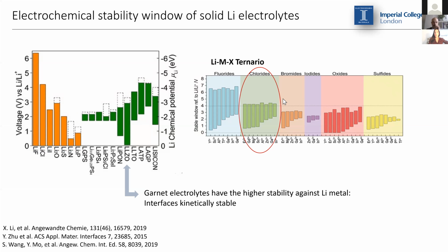If we look to the chlorides, this electrochemical stability window increases a lot, and they are actually very good at high voltages, but they don't have good stability at low voltages, and they are not stable against lithium metal. The only electrolyte that seems to be stable against lithium metal are the garnets that create an interface that is kinetically stable with lithium metal.